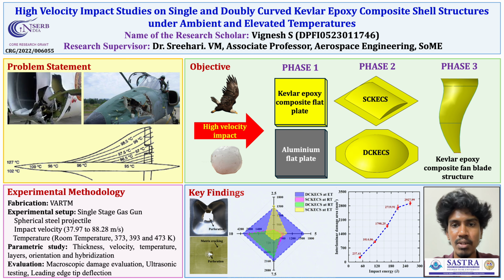The interlaminar damage area of the doubly curved Kevlar-Epoxy composite shell structure at 48 joule at elevated temperature exhibits a higher damage area when compared to others. At the elevated temperature, the epoxy reaches its glass transition temperature, which makes the projectile rebound after impacting all the structures, whereas it perforates the structures at ambient temperature impact.